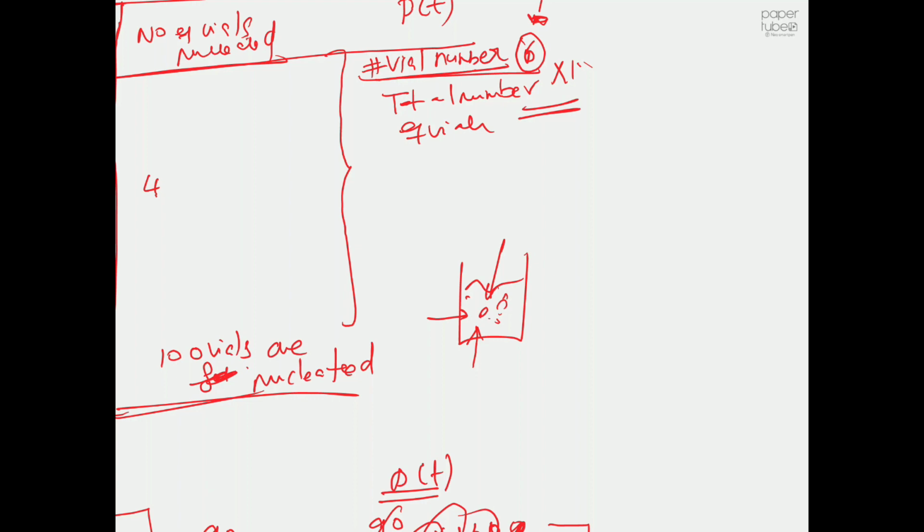But we will get this number mathematically once we manage to capture the stochastic nature of the time using a probability distribution function, which is given by, let me check one time, I don't want to make any mistake. It's given by the probability of your vials getting nucleated, which is a function of time, equal to 1 minus exponential of minus Jv into (t minus tg).